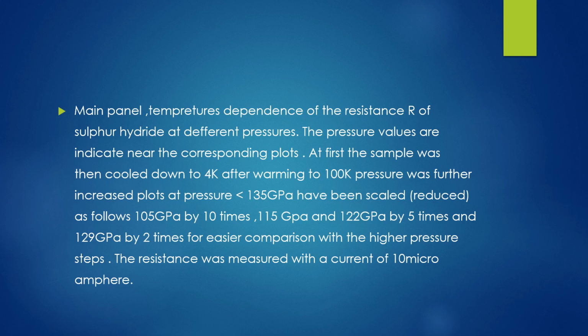At first, the sample was cooled down to 4 K after warming to 100 Kelvin. Pressure was further increased. Plots at pressure less than 135 gigapascal have been scaled as follows: 105 gigapascal by 10 times, 115 and 122 gigapascal by 5 times, and 129 gigapascal by 2 times, for easier comparison with the higher pressure steps. The resistance was measured with a current of 10 microampere. Now these are the results we obtained from the superconductor.